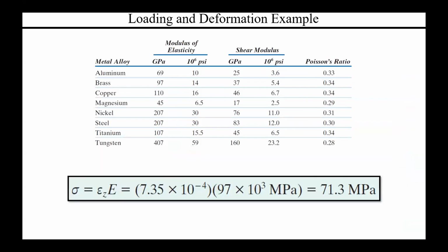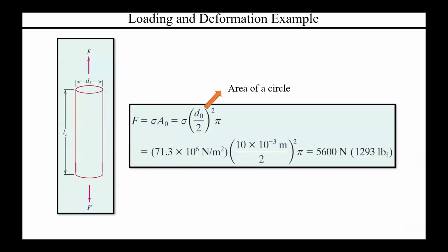You can then solve for the stress in that Z direction. Along that tensile direction, you solve for the stress by using the elastic modulus coupled to the strain in Z, giving you your stress. But ultimately, what we wanted was the magnitude of the load, not the stress itself. So that would be force. You need to understand that this is a circular area, and because the force is applied perpendicular to that plane, that's where the force actually comes from. That's why your area in this case is the area of a circle, and you plug your values in and you get your final solution.